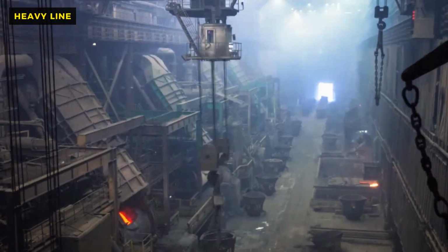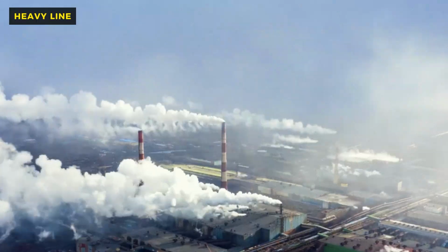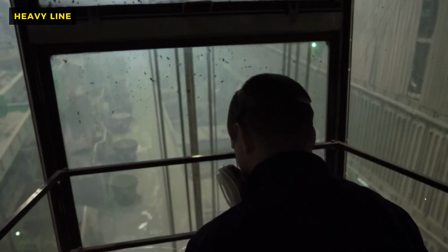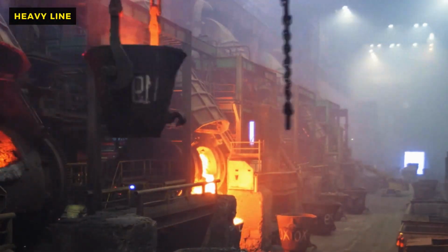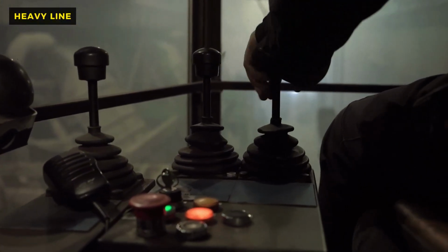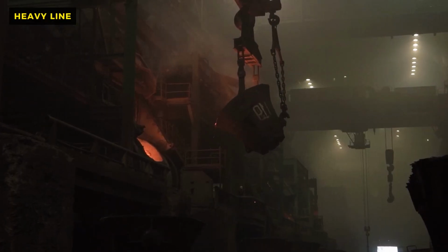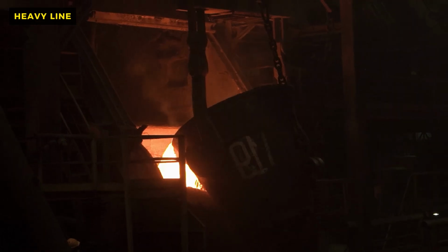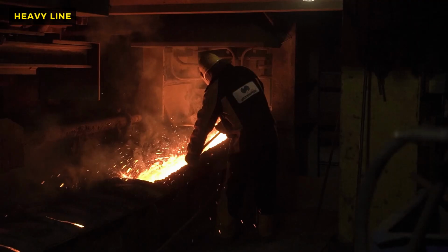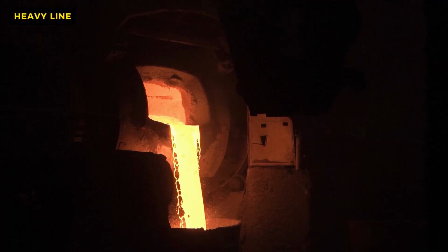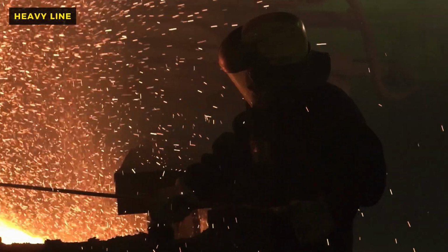The concentrate is dried until it contains less than 1% moisture, a critical step because any water entering the furnace could flash into steam and cause a catastrophic explosion. Imagine throwing a cup of water into a deep fryer, but scale that explosion up to the size of a 5-story building and you begin to understand the danger.